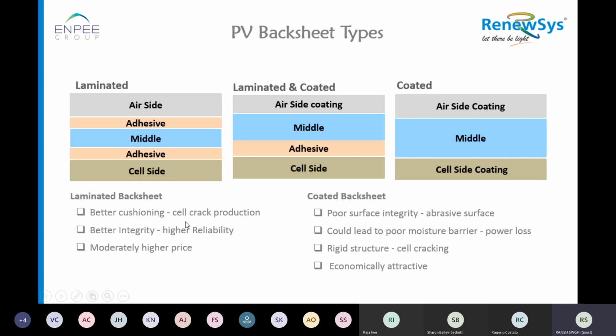Laminated back sheet should be preferred because of the cushioning effect, which provides less cell cracking. It gives better integrity because it is carrying more mass, more polymeric material with more toughness, and it is moderately priced. Whereas coated back sheet is poor in surface integrity because the surface of the back sheet is coated. This could lead to poor moisture barrier because the layer is one, it is not a laminate of film, and any coating has got porosity, it gives away the moisture through it. Then the rigidity of the back sheet is more because of no cushioning layer, so it can lead to cell crack. Of course, this is economically attractive because the cost of manufacturing is less, being two layer coated or one layer coated.